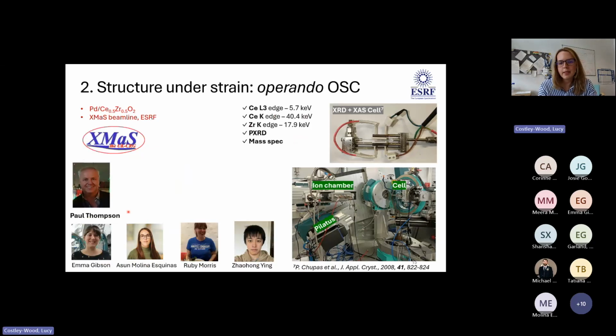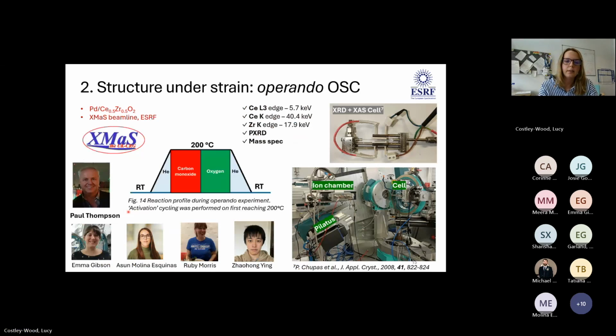We wanted to go to XMaS in particular because, unlike the beamlines, for example, here at Diamond, we can measure both the cerium L3 edge and the cerium K-edge. So we can obtain both a more XANES-sensitive edge and a more EXAFS-sensitive edge. We can also measure the zirconium K-edge, the powder diffraction, and have a mass spec monitoring the experiment at the same time. This is the reaction profile, so the regime that we followed.